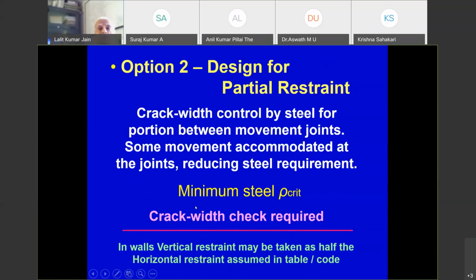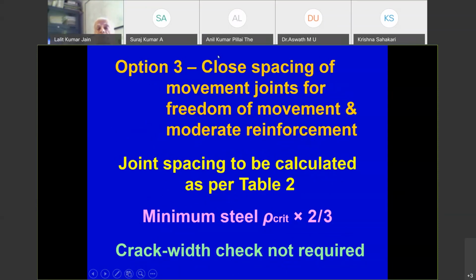Now, we will not go into much detail, but this is all as per the 2009 code, which was already there. And there, the steel will be more or less what we call rho critical. That much steel we have to provide. Now, if you take option 3, if you are very close to the spacing of joint, the other interpretation is when you have a very small structure, about 7 to 8 meter size only, that is a very small structure. Your minimum steel can be 2/3 of the specified. Whatever the minimum, you can go less than that. So if the spacing of joint is very small, or your tank itself is very small, you can save on this steel.